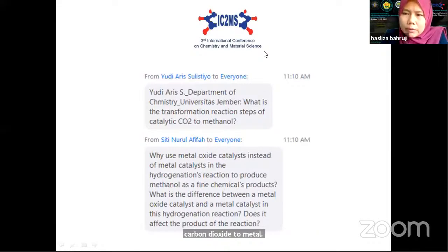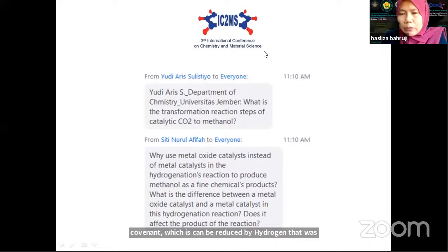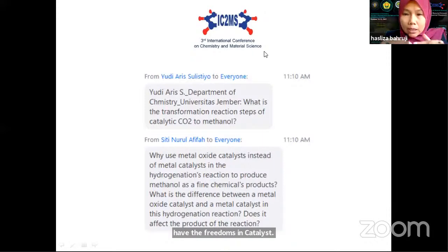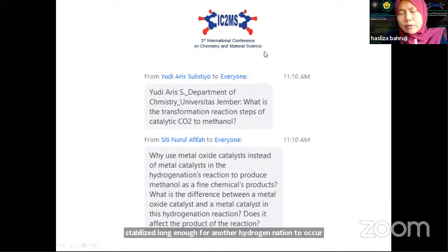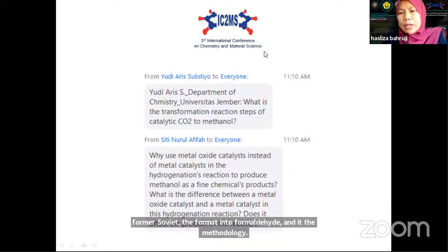Yeah, as we show in our TPD analysis, the first important part is CO2 must be absorbed on the surface. While it is absorbed, normally it will form this bidentate carbonate, which can be reduced by hydrogen that was dissociated on the palladium surface. So this bidentate carbonate will be transformed into this intermediate that we call formate intermediate. This formate intermediate is very important because this is the key point, whether it will be transformed into methanol or converted into carbon monoxide. So if you have this palladium zinc catalyst as an active center, it allows the formate intermediate to be stabilized long enough for another hydrogenation to occur to convert formate into formaldehyde and finally to give methanol. So this is basically the reaction step from CO2 to methanol: CO2 from bidentate carbonate into formate, into formaldehyde and into methanol. That's basically what we understand so far.